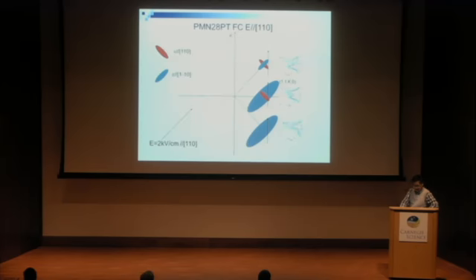And near the 1-10 Bragg peak, the strong blue wing is even stronger, which crosses the top. So here we have an idea that the 110 field will enhance the blue wing, which comes from local polarization along the 1-10 direction, and suppress the diffuse scattering coming from local polarization along the 110 direction.